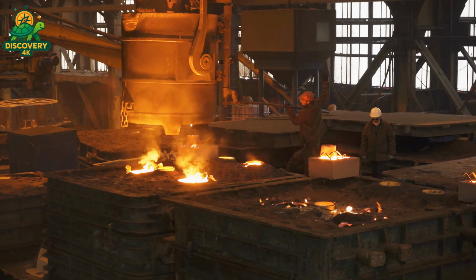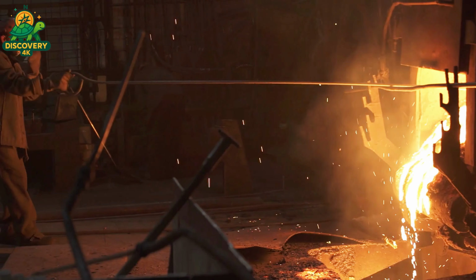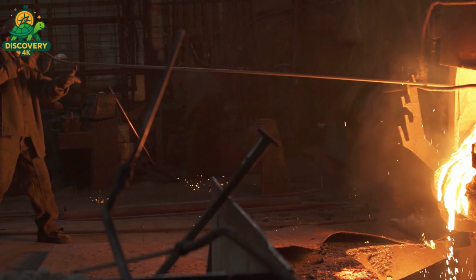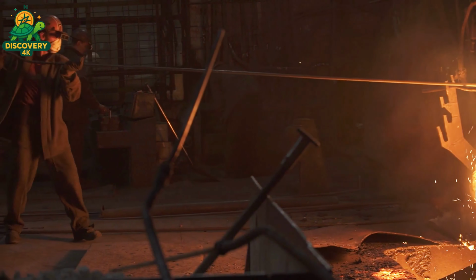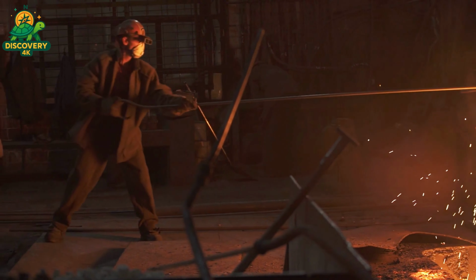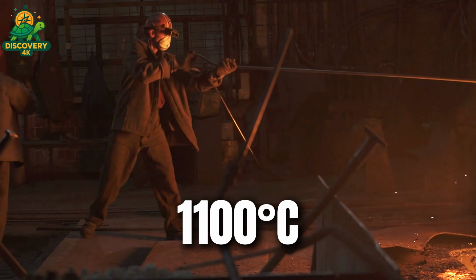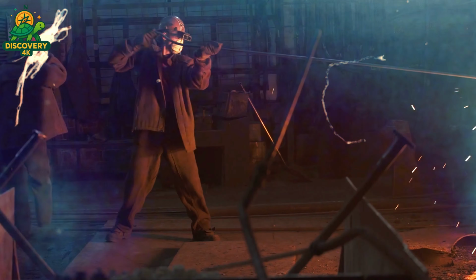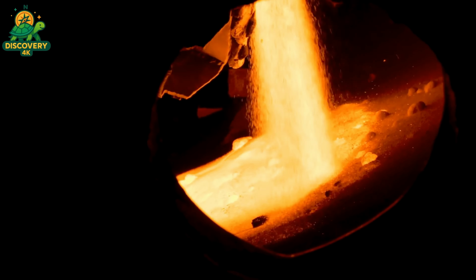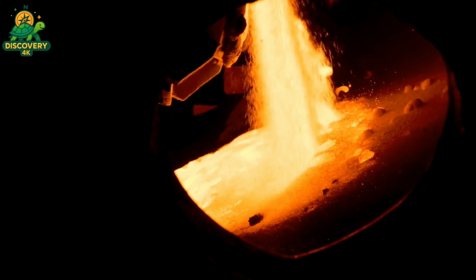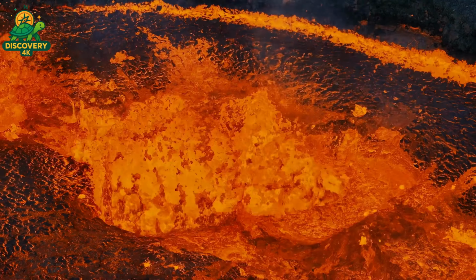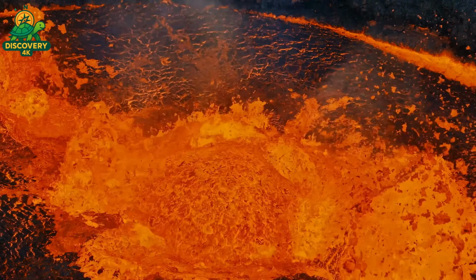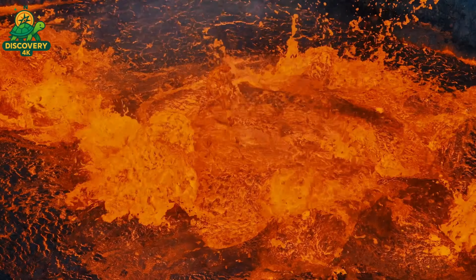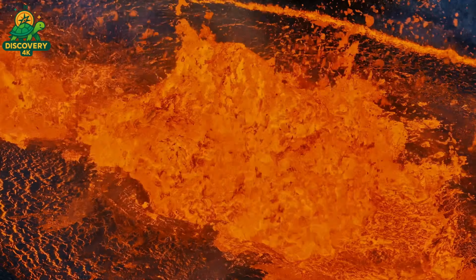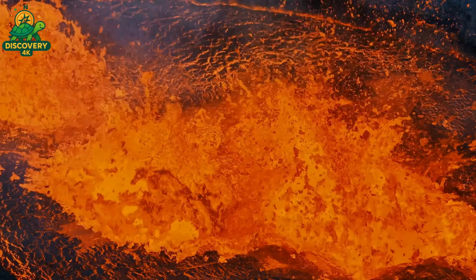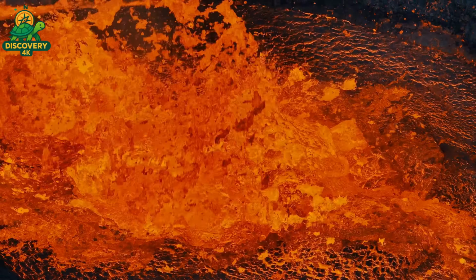Inside, it melts slowly over several hours, transforming from a grainy solid into a smooth, homogeneous liquid. Here's what happens inside. At around 1,100 degrees Celsius, the sand begins to soften and fuse. As the temperature rises, individual grains dissolve and bubbles form and rise. Around 1,300 degrees, the mixture becomes fully molten and impurities are gradually released. By 1,500 degrees Celsius, the batch has become a glowing orange liquid glass, flowing like lava.